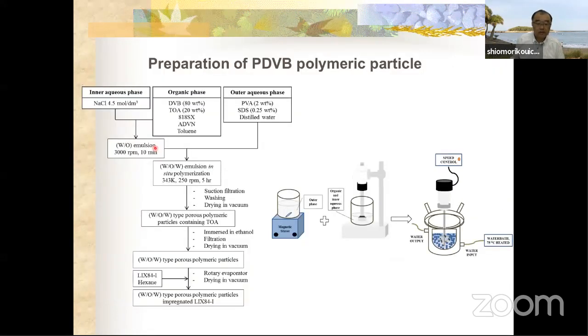So I will show the preparation method shown here. Initially we make a double emulsion. The inner phase is a sodium chloride aqueous solution. The organic phase is a monomer solution like this. After preparation of the W/O emulsion, the W/O emulsion was dispersed in the outer aqueous phase like this.